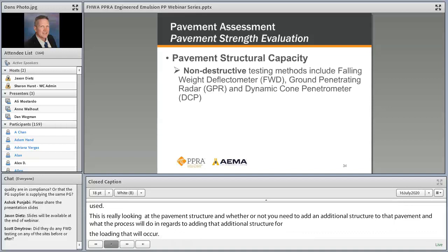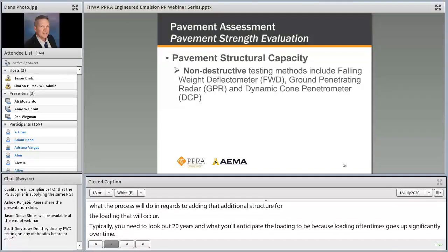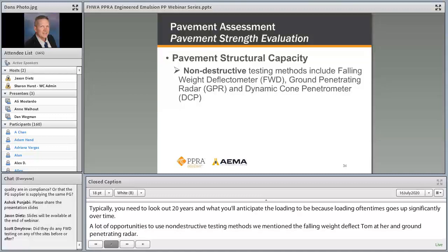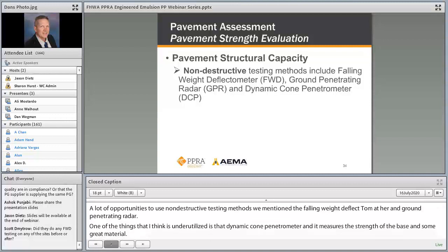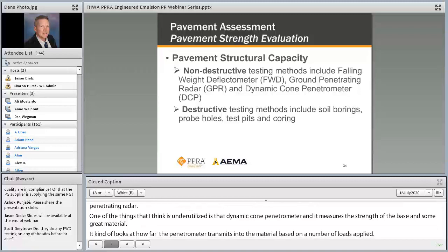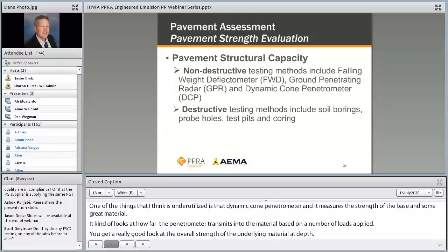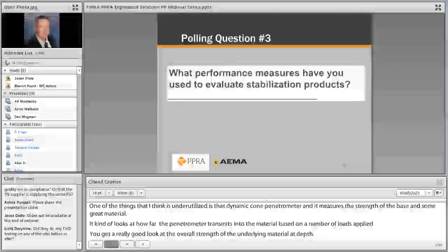A lot of opportunities to use non-destructive test methods. We mentioned the falling weight deflectometer. We mentioned ground penetrating radar. One of the things that I think is underutilized is the dynamic cone penetrometer, because that allows you to go through a core hole and actually measure the strength of the underlying base and subgrade material at depth, just kind of looking at how far that penetrometer penetrates into the material based on the number of blows that are applied. So you get a really good look at the overall strength of that underlying material at depth. And then there's also destructive testing methods that include soil borings, coring, test pits, probe holes, and similar things like that.